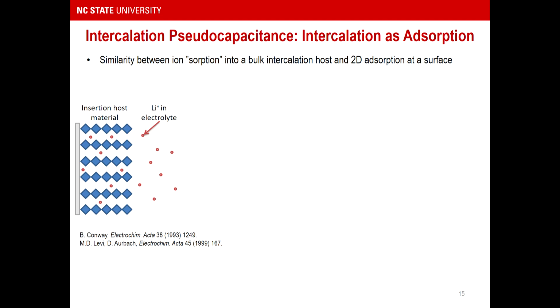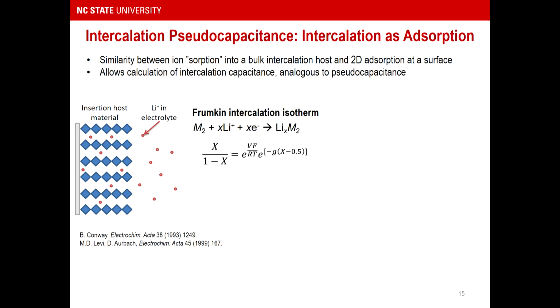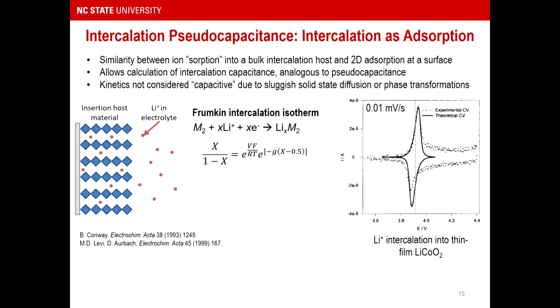And so as this intercalation concept took hold, the pseudocapacitance community, or folks that thought about adsorption and desorption at surfaces, saw similarities between that process as being essentially an ion sorption into a bulk host, and that you could assign an intercalation capacitance, or what would be analogous to a pseudocapacitance, using exactly the same type of Langmuir or Frumkin intercalation isotherms, for example. However, oftentimes we don't think about these kinetics as being capacitive, that is, being limited by surfaces, because solid-state diffusion dominates in most of these materials, or phase transformations take hold.